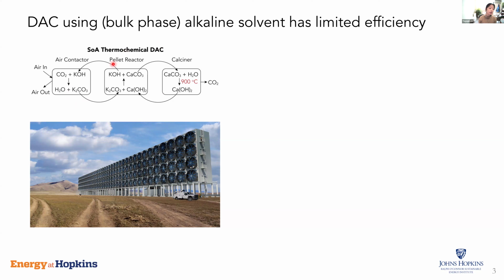And then in the incumbent thermochemical method, we'll have a pellet reactor to go through what we call the calcium looping step, where we regenerate our potassium hydroxide using calcium hydroxide. In this case, we'll form calcium carbonate as a byproduct. And in order to recycle the calcium, we'll send it through a calciner at usually 900 degrees Celsius to bake a pure CO2 off and regenerate calcium hydroxide to complete the whole loop. But the challenge is that this process is really energy intensive because of this high temperature calcination step.